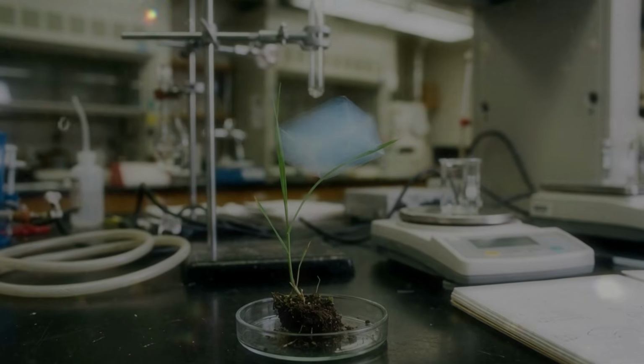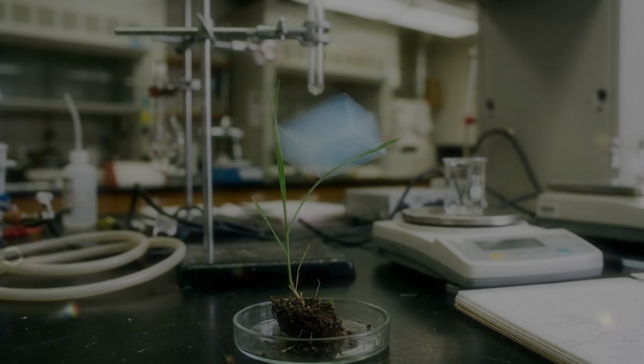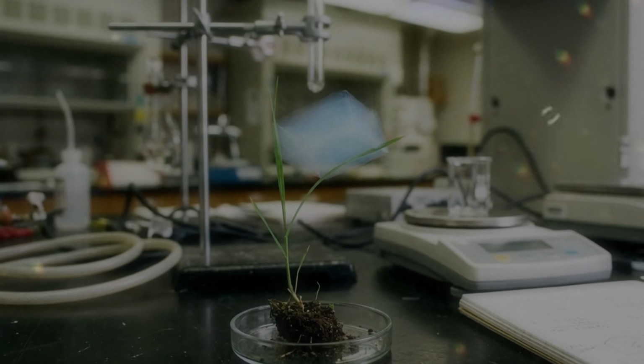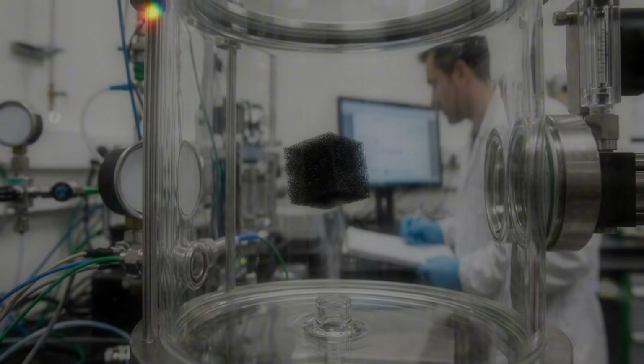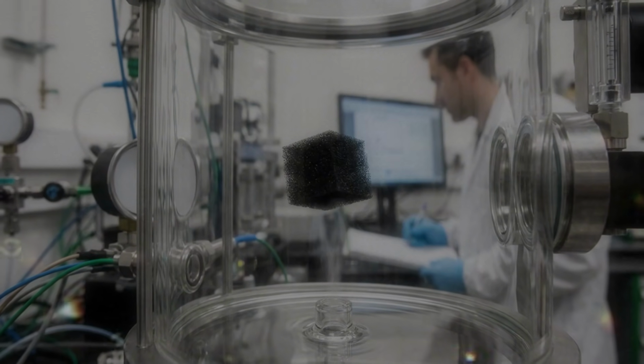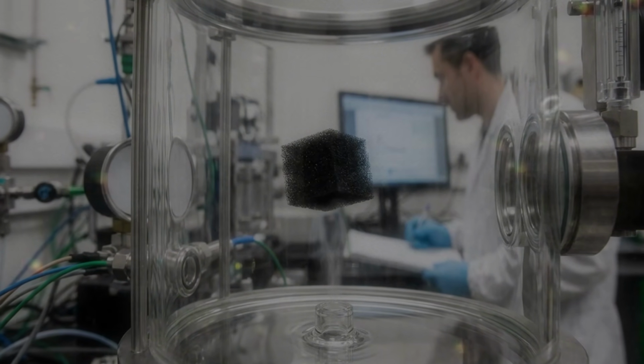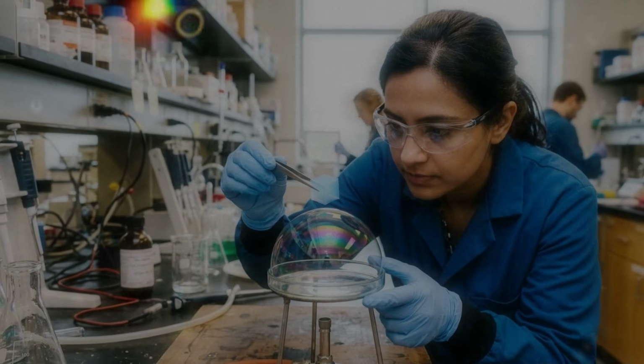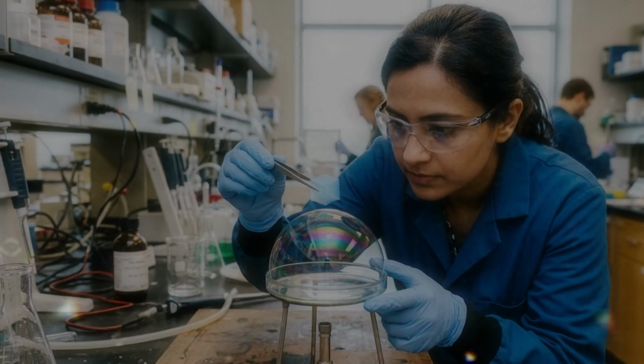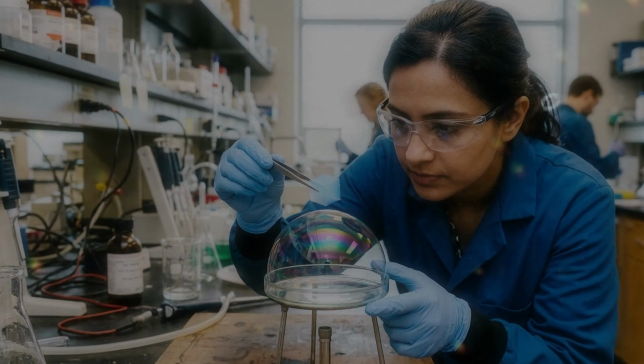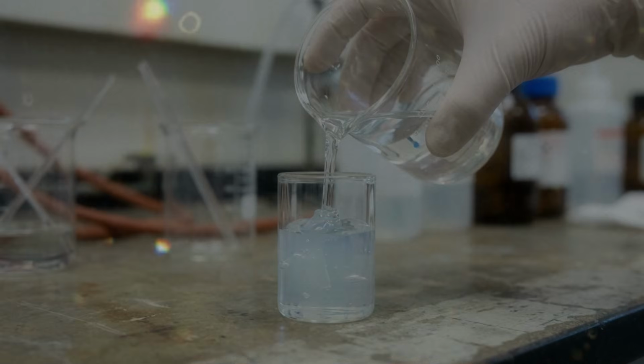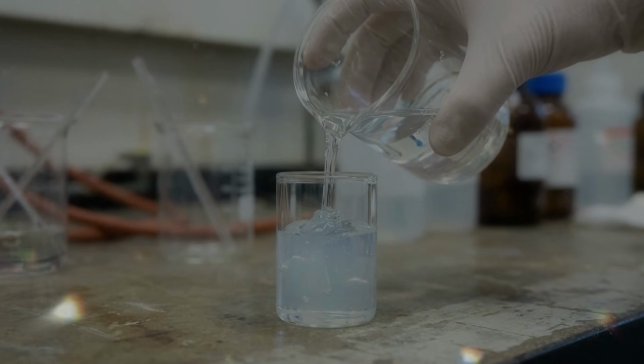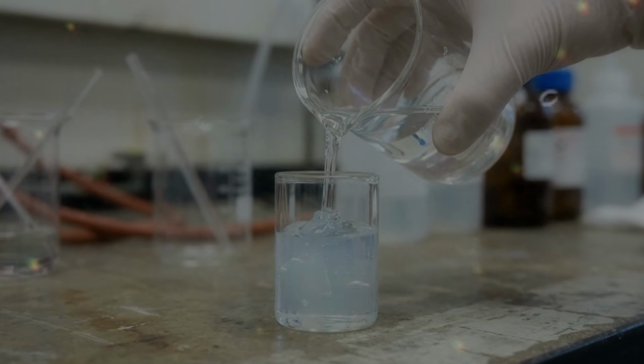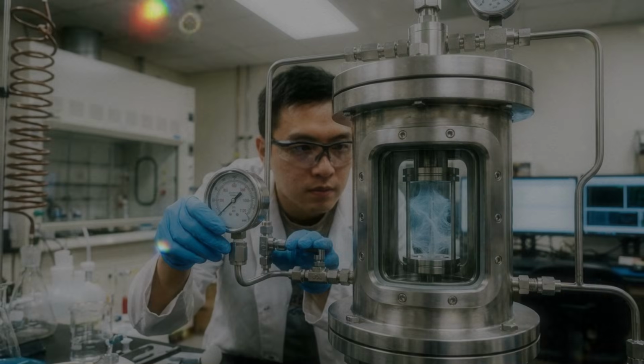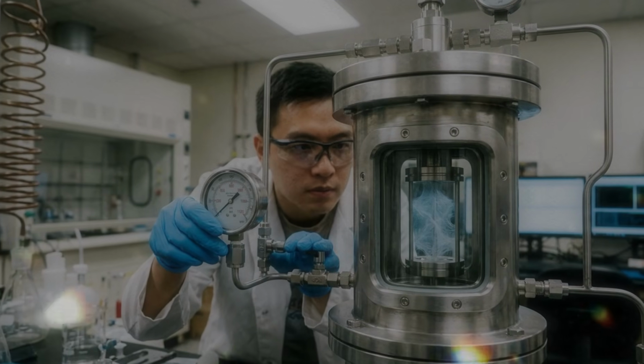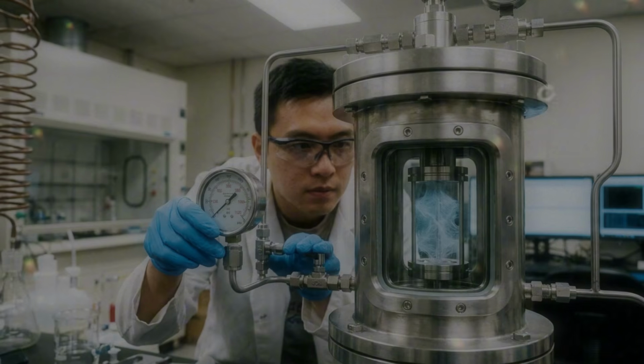Scientists can modify the network depending on which movement matters most. Smaller pores for insulation, better carbon contacts for conductivity, curved walls for recovery, fibrous reinforcement for sound and vibration. They can add particles that absorb radiation, chemicals that react with pollutants, metals that store electrical charge, or polymers that prevent cracks. The aerogel becomes a platform rather than one finished product. This flexibility is why so many possible uses have been proposed.